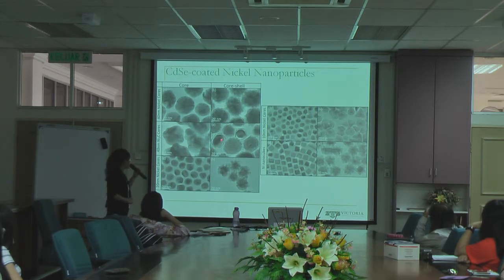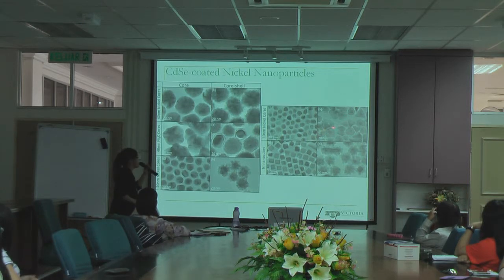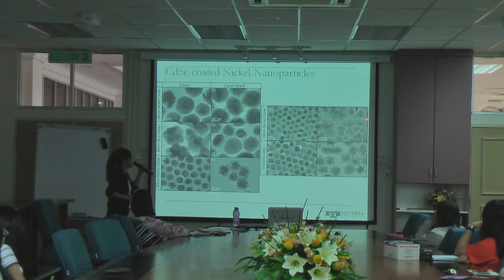For the nickel carbide, it is a quite different scenario. If you look closely, you find that most of the cadmium selenide domains are plate-like. They are not like spherical particles like the other cases, but they are plate-like particles, which is quite interesting. And for the 10 nanometer nickel cores, it's also a very different morphology for cadmium selenide. Essentially, the cadmium selenide domain grows into a much larger size, up to 20 nanometer, and it fully encapsulates the nickel seeds. So next, the question is, why are we seeing these kinds of similarities, and why are we seeing something different in some of the cases?